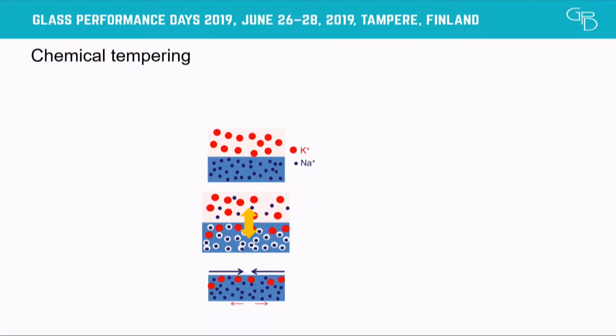But now I want to switch to what chemical tempering is and why we need chemical tempering. Because clearly, being so thin, it means that the glass will break very easily. So chemical tempering is also known as ion exchange. What you do is put your glass into a bath of molten salt. This molten salt is potassium nitrate. And at a temperature of 450 degrees, the potassium ions can exchange their position with the sodium ions in the glass. And these particles are much larger than the sodium. And so by taking a larger place, they create precompression.